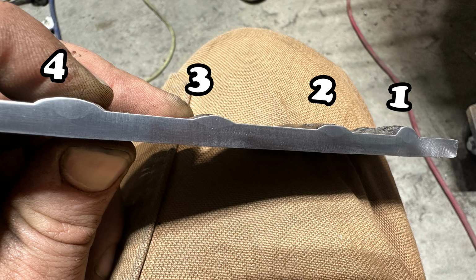Maybe the super hot is a little bit better, but 2 and 3 really, I would argue, have less depth of penetration. The profile of it is wider and more rounded, which is good. So sidewall fusion would probably be better on a fillet weld, but the actual depth of penetration isn't really better on 2 or 3. And you got to remember, 3 was 750 degree preheat.